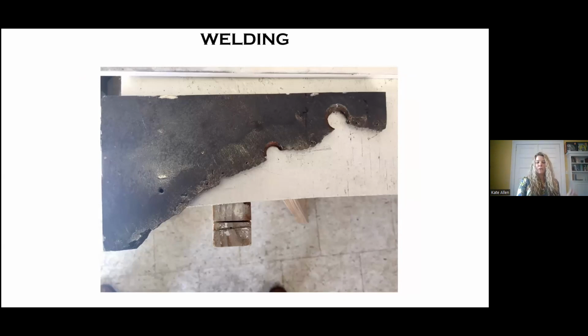This is my opinion: we feel that welding's not a great repair for the field. It can work well for heavier castings, but it is really best suited as a shop repair. The need to preheat castings slowly and uniformly is just so critical. It helps reduce the risk of thermal shock on the cooling. And if castings aren't heated and cooled properly, you face the risk of the weld failing. This is what we see. This is a failed weld from the 60s. It's very difficult to do in the field.